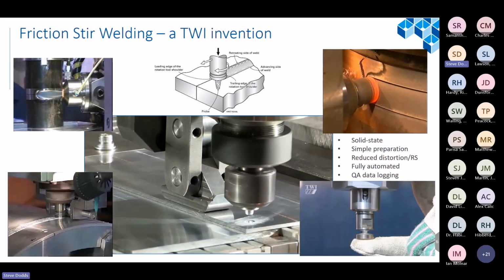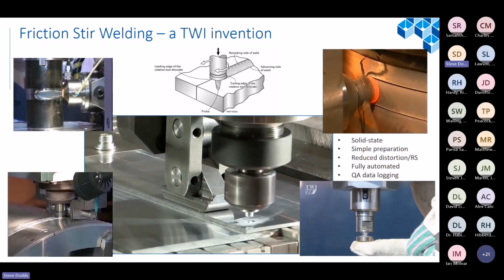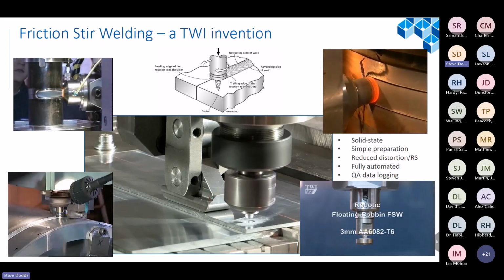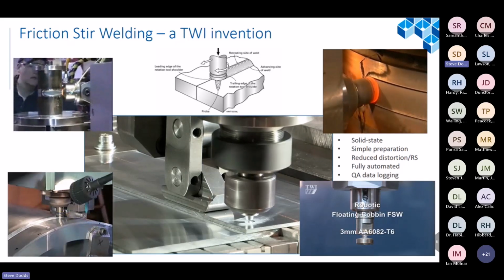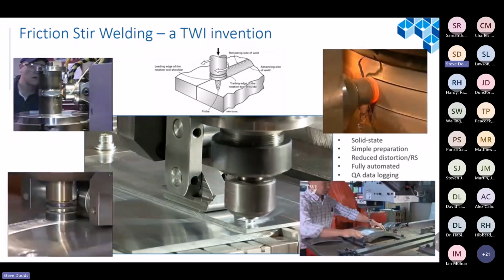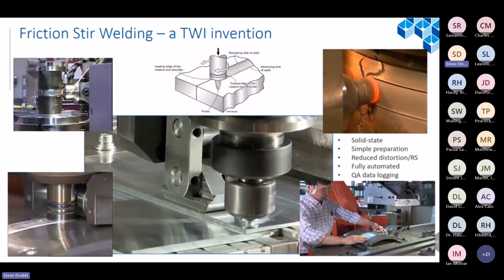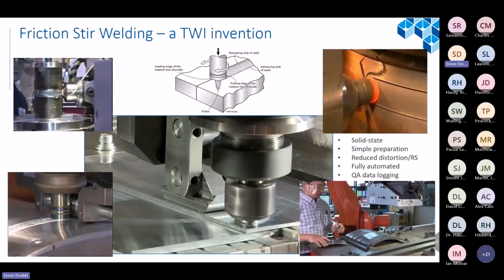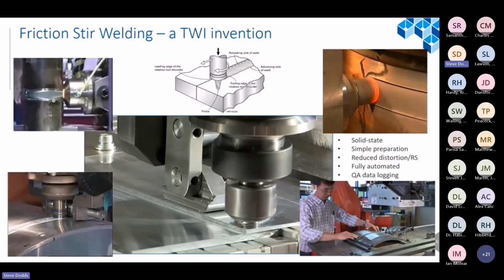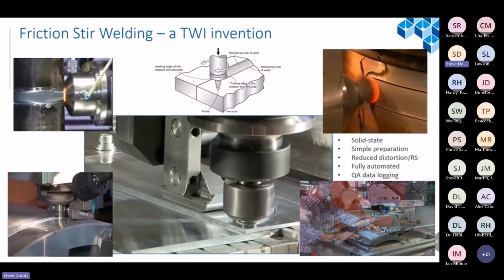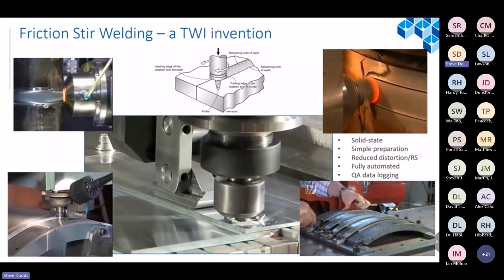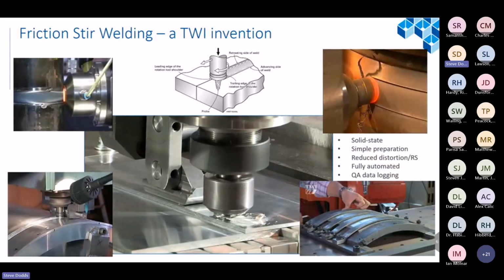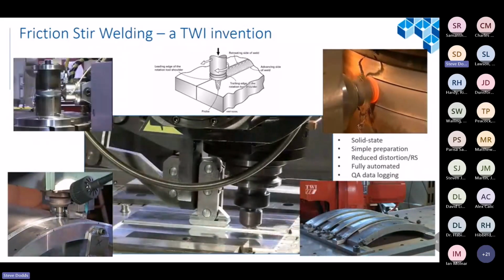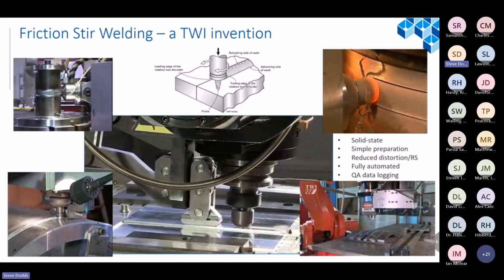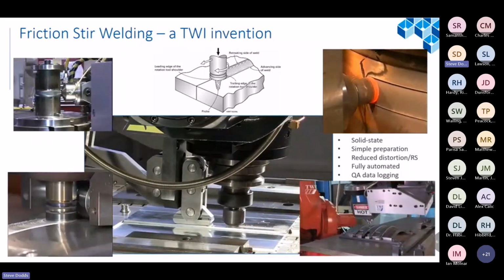The central picture offers you the most detail for a simple joint, but the other ones around the screen show a variety of circumferential welds and also a bobbin weld, which nips from both sides and you can weld without having to use a backing plate or resistance from the face. The most interesting one for this meeting is the top right, and what you're seeing there is a friction stir welding tool spinning around, or should I say the canister is spinning around against the head of the friction stir weld. And that is a very typical finish of a friction stir weld.